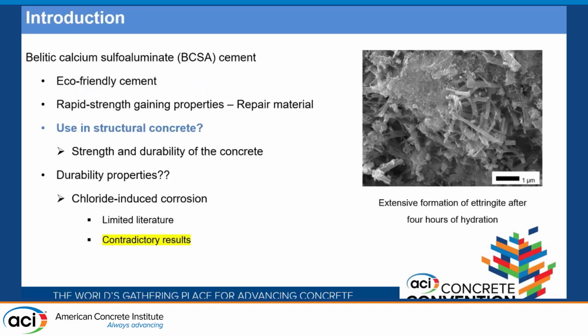So Belitic calcium sulfoaluminate cement is an eco-friendly cement. It has rapid strength gaining properties which are due to the extensive formation of ettringite as the early age hydration product. The image on the right shows the extensive formation of ettringite crystals after just 4 hours of hydration. So this rapid strength gaining property is one of the reasons why BCSA has been used as a repair